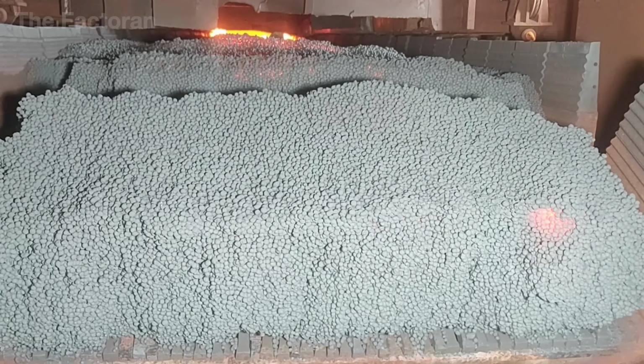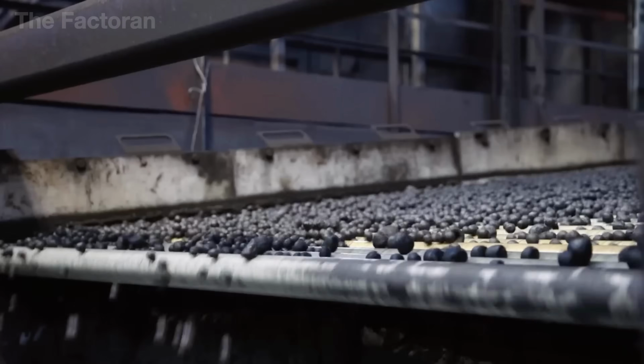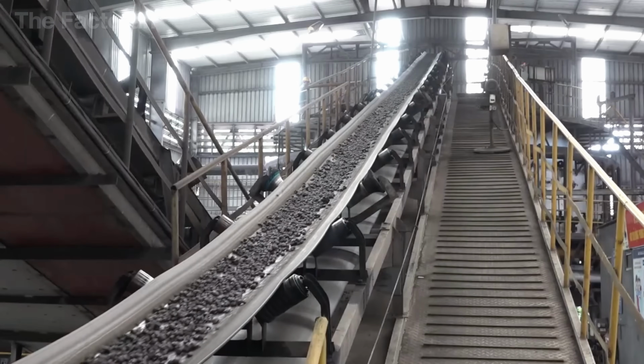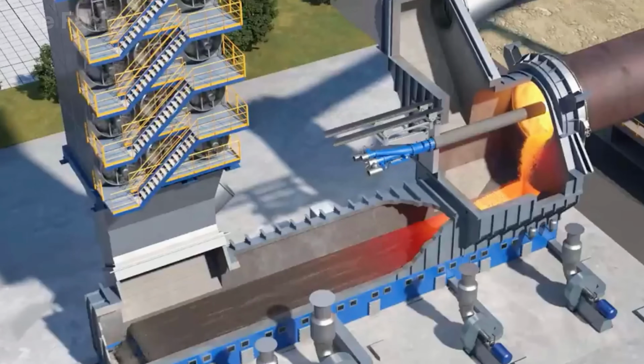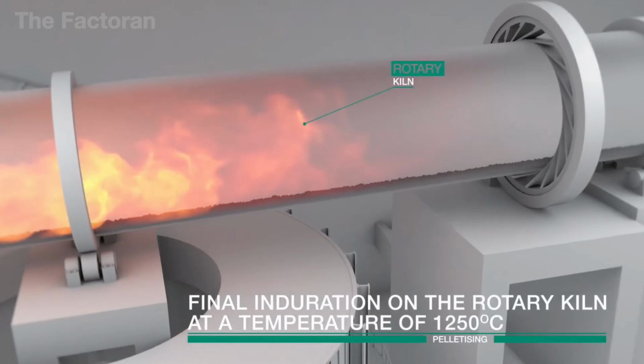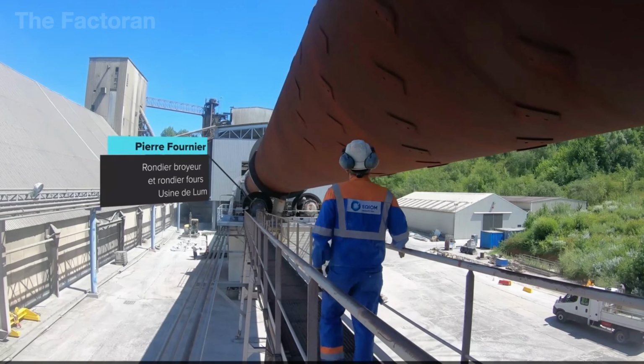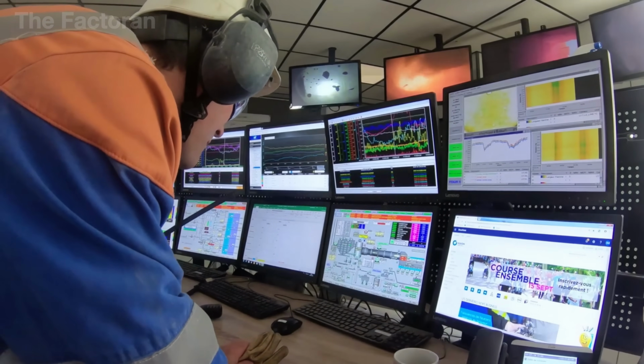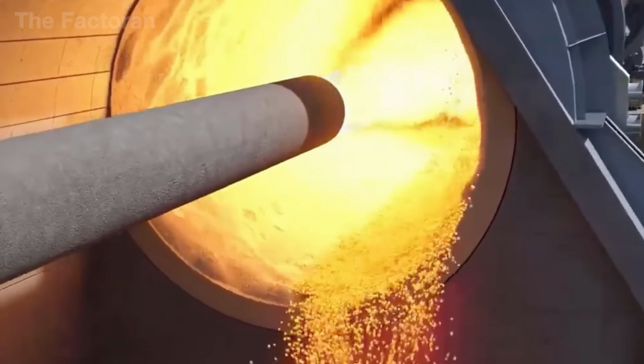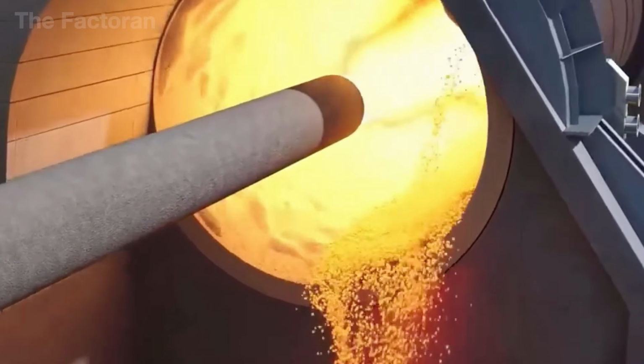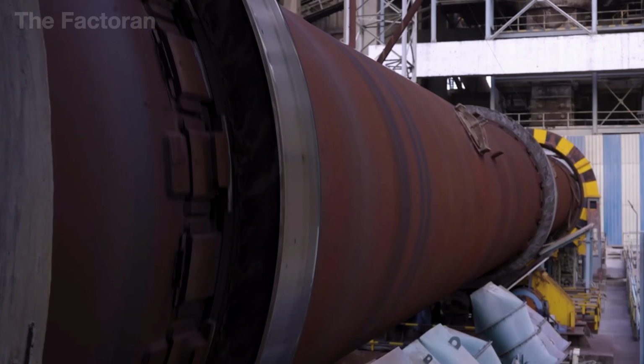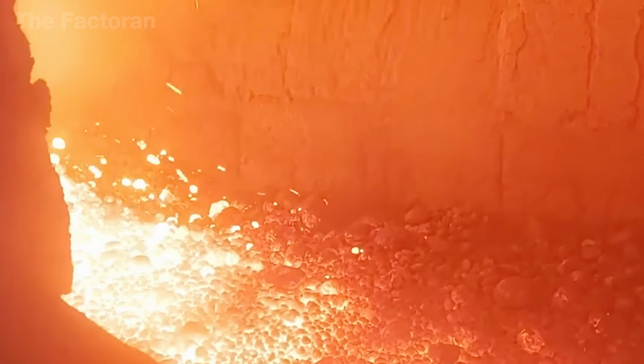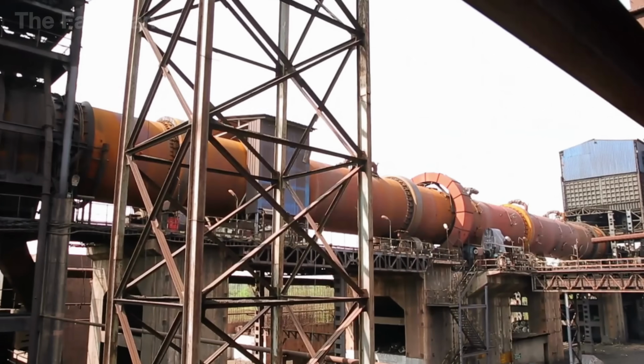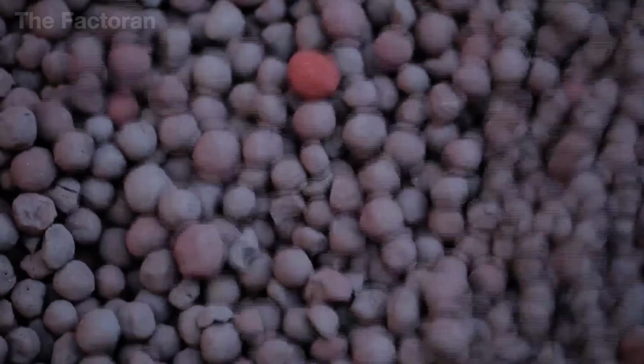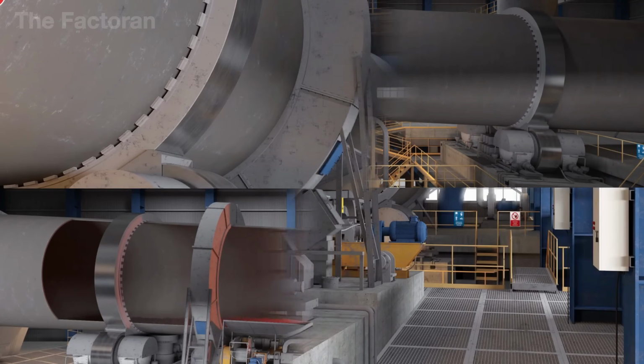From the great conveyor, the glowing red pellets continue their journey into the rotary kiln, a colossal steel cylinder stretching dozens of meters, set at a slight incline and turning slowly on its axis. Inside, flames shoot from the kiln's mouth, sweeping the entire length and turning the chamber into a blazing river of heat. As the drum rotates, the pellets tumble and roll evenly through temperatures ranging from 1,200 to 1,350 degrees. This constant motion ensures each pellet is baked uniformly from core to surface, eliminating weak spots or cracks. Impurities and residual dust are burned away, while the ore particles fuse together into a dense, solid structure.